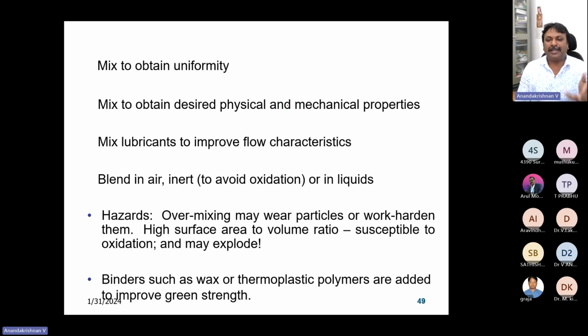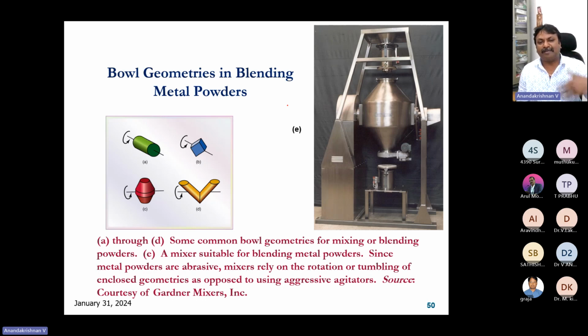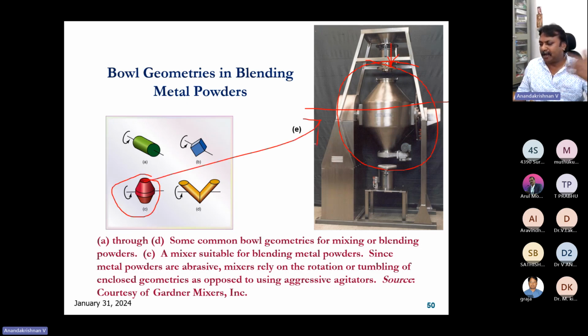And then you cannot blend in air. So sometimes you have to blend it in an inert atmosphere. You may need a toluene-like liquid to fill. Then, when we want a very good mix of this powder, for different alloys we want to make, there are different shapes available. You can see a double conical container where powder is fed from the top. You close it and it rotates about the horizontal axis. So you can easily blend the powders. Either you can use a cylindrical vial or container, or a cube vial rotated about its diagonal axis, or a double V type blending bowl.